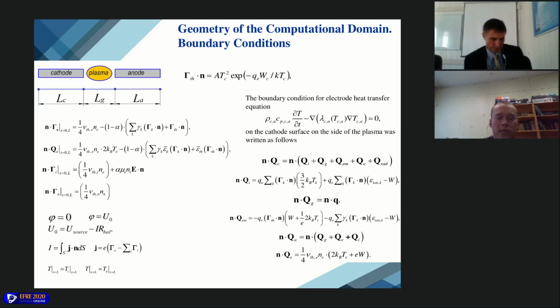The boundary condition for this equation on the cathode surface on the side of the plasma was written in this form. The first term on the right hand side describes the density of ion energy flow to the cathode. It includes the density of the kinetic energy of the ions, mainly in the cathode layer, and the density of potential energy which, when transferred to the cathode, is caused by neutralization of the ions. The second term on the right hand side describes the density of the thermal flow from the heated gas near the cathode.